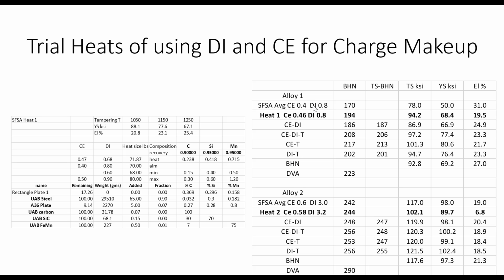My average properties are here. This is the actual heat properties that I get. And then these are the predicted properties using the different correlations we talked about. If I just look at correlations with Brinell hardness, I'm really not very far away, as you'd expect. The worst one is elongation, and John Griffin pulled these and said that all these specimens had porosity in the fracture, so they're not a good test for elongation. So I think the elongation stuff is pretty meaningless in this.